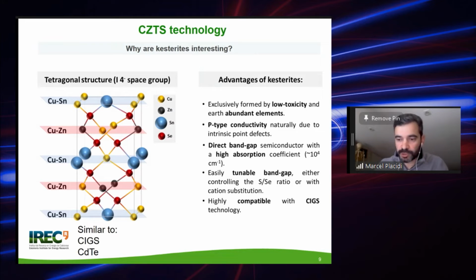And this is very important because currently there exist production lines for CIGS and for cadmium telluride. So in case of a demonstration of a very high efficiency with kesterite, this is very good because since the kesterite structure is very similar to the CIGS and the cadmium telluride one, the transfer from the lab to the industry is quite an easy task. And this is very important for this material.